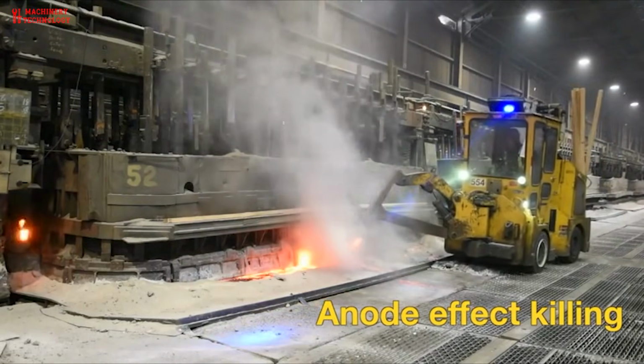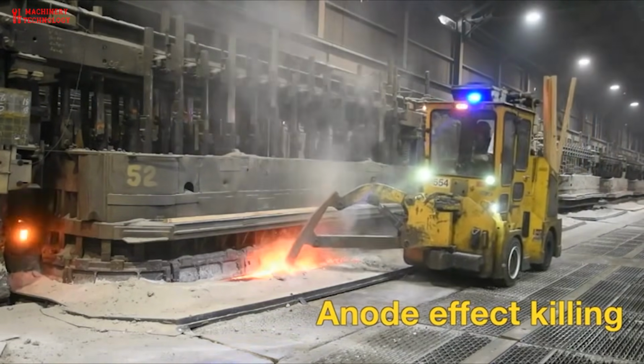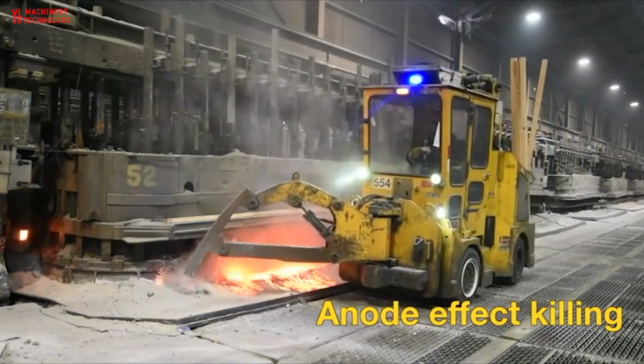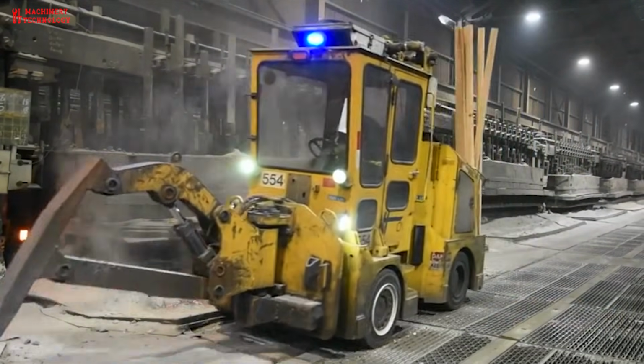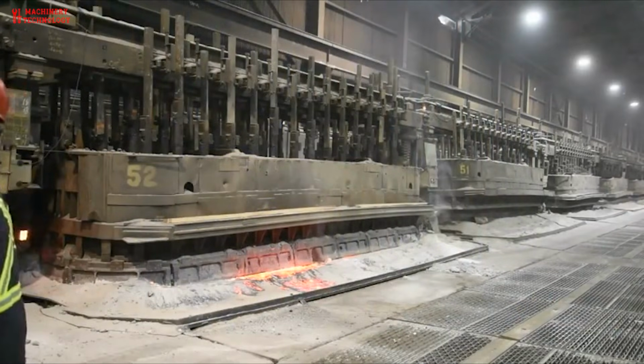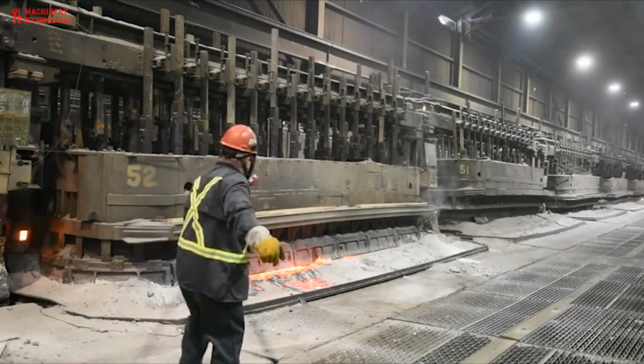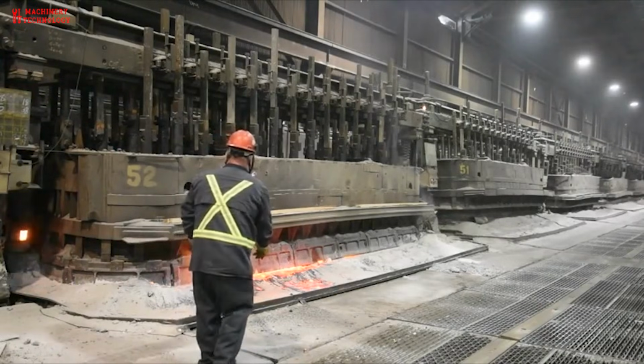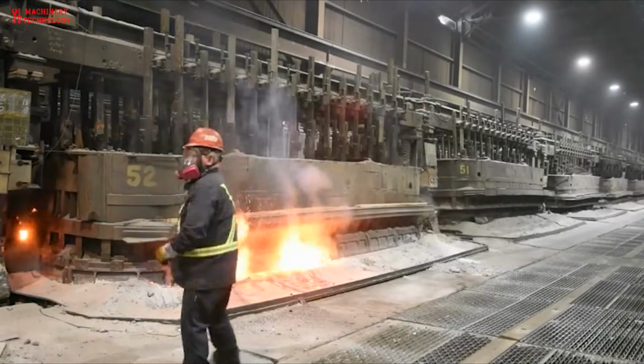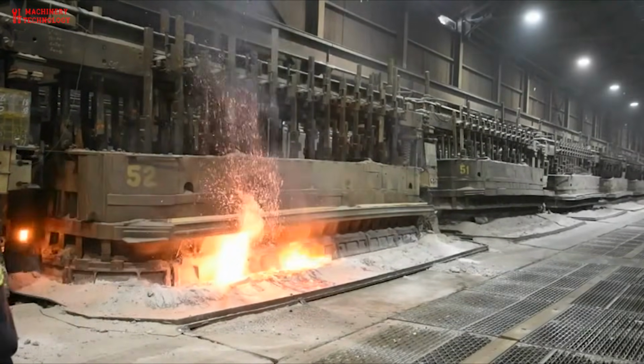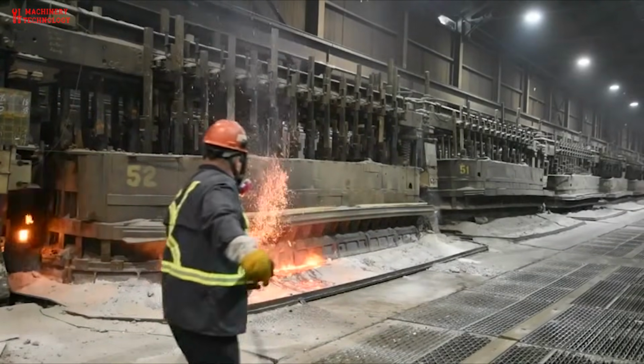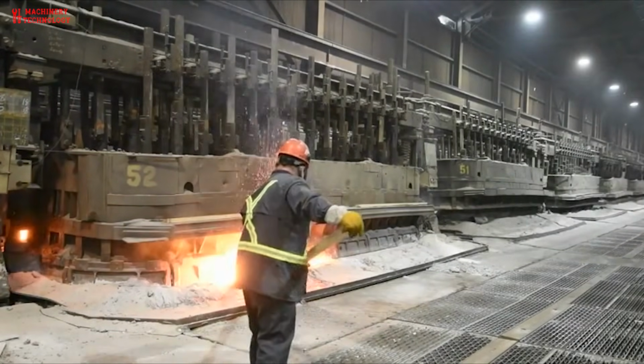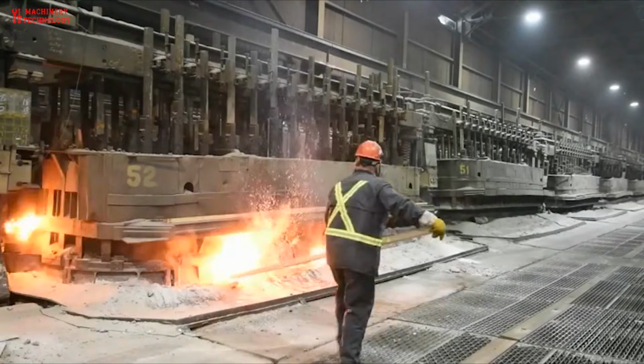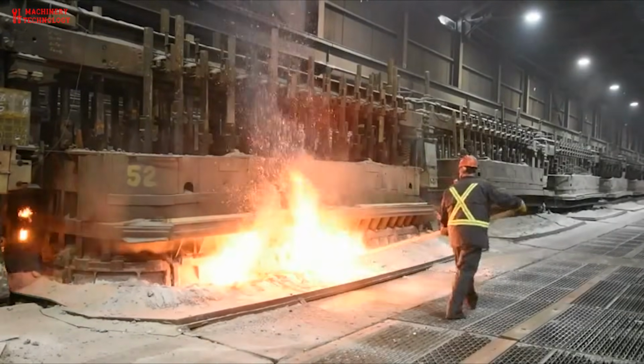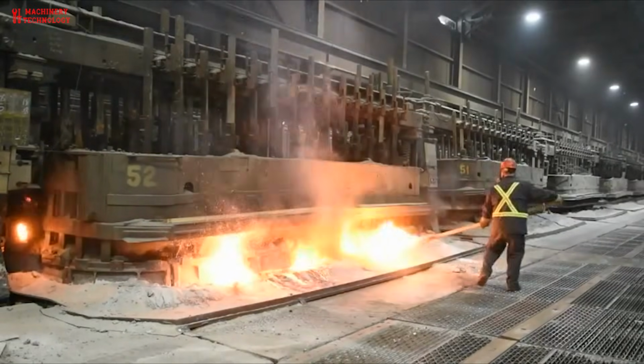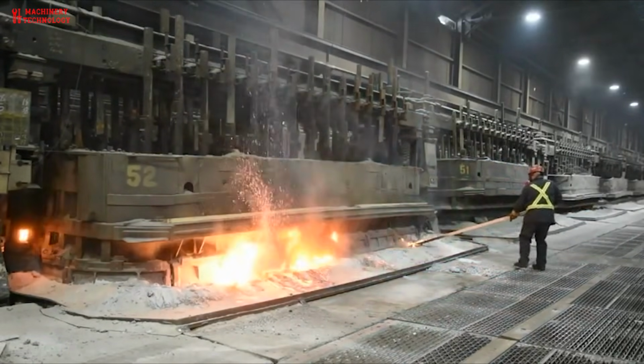Anode effect appears when alumina in the pot falls too low and the cryolite bath can no longer carry current smoothly. The voltage rises, gas builds beneath the crust, and the pot begins to hiss and glow with an unstable flame. Killing the effect is essential because if it lasts, the excess heat and emissions can damage the lining and waste energy. To correct it, operators feed fresh alumina and break the crust to release trapped gases, restoring the calm path for electrons at the bottom.